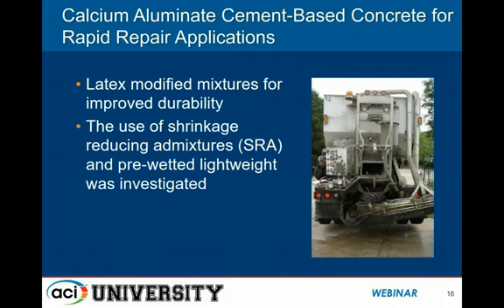So what was investigated there was a calcium aluminate-based product. Calcium aluminate cement has been around for quite some time. It actually dates back to the 1800s, and so it's not a new product. But what happened in the early part of the 20th century was that it was discovered that this cement had a drawback where the strength would diminish over time. And this is a process called conversion. This conversion process meant that if we built structures out of this calcium aluminate cement, it would potentially have a strength diminishing behavior, which could then lead to the risk of collapse over time.